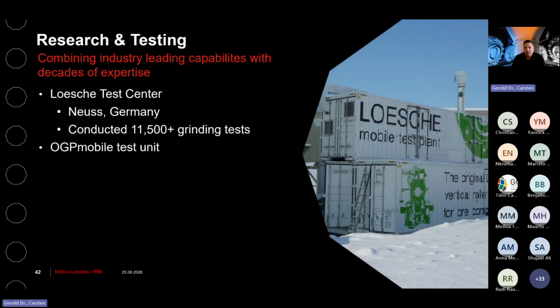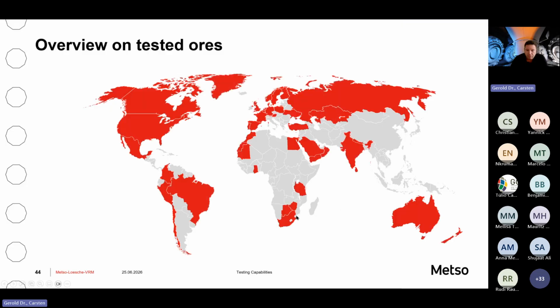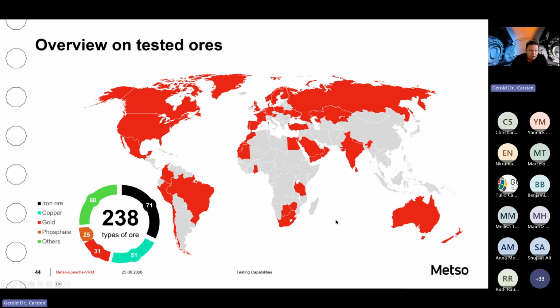Speaking about test capabilities, we have at the moment 2 places where we can test the vertical roller mill. It's going to be more, but at the moment there's the Loesche Test Center in Neuss, and we have a mobile unit which is called the OGP Mobile. You see here on the right hand side, and up to now we tested ores from a lot of areas in the world. In total it's 238, the majority of them being iron ores, followed by copper ores, phosphates, gold, a lot of others, nickel, tin, zinc, manganese.